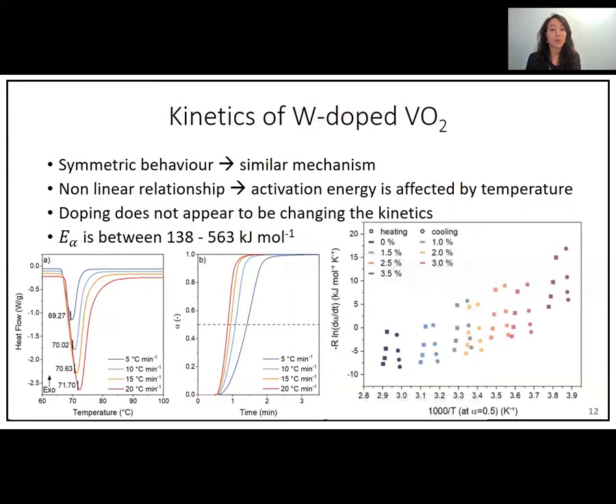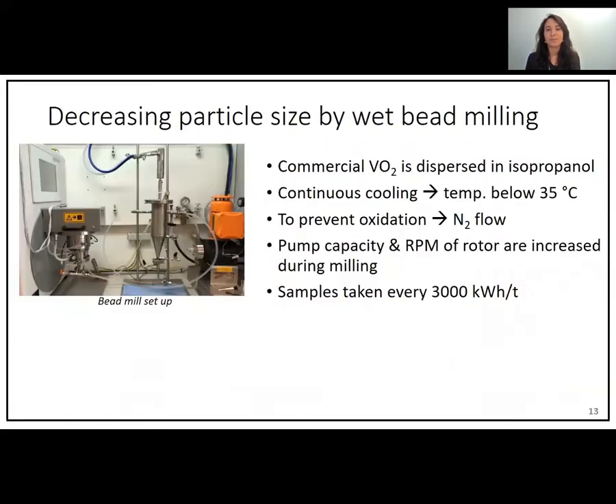The non-linearity is just the fact that activation energy is affected by temperature. Additionally, combining all the Friedman plots for the doped VO2 results in a very similar activation energy, which ranges between 130 to 560 kilojoules per mole. This value depends on temperature, so it also makes it a bit difficult to compare the values. The similarity in the plots also suggests that the doping does not affect the kinetics of the structural phase transition.